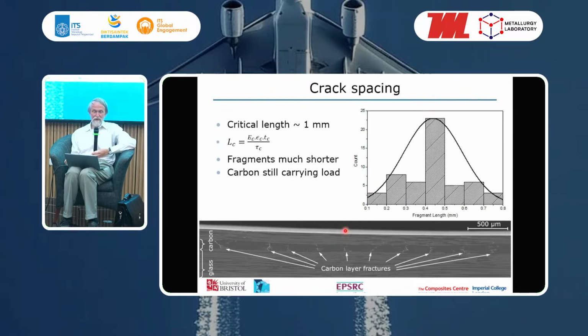So one of the interesting things is to look at the spacing of those cracks. So this is a histogram of the fragment lengths along the length of that M55 specimen. And you can see that it's of the order of about 0.5 millimeter plus or minus a bit.